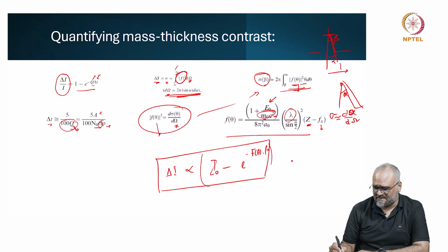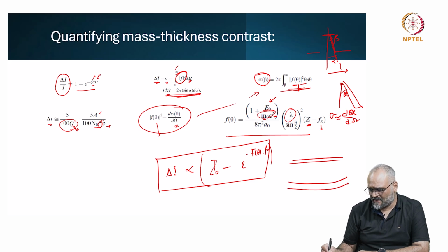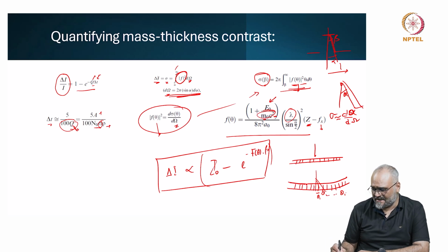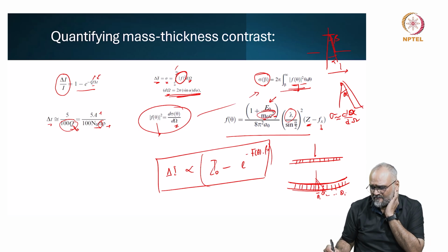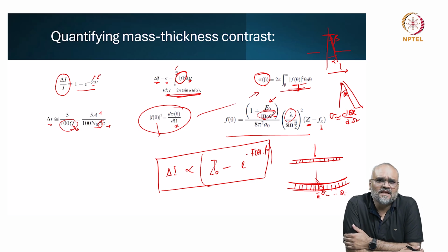Also, if I have a specimen which is very thin, when I place it in vacuum, it tends to somewhat bend a little, and if I look at the arrangement of atomic planes within a specimen which is bent at a certain angle and which is oriented exactly at a specific angle to the electron beam, let us say I have some variation in the angle with these planes here, if I call this as some theta 1 and this is some theta 2 and so on as theta i, this bending also causes a change in the Bragg diffraction condition for the planes that are arranged internally within this specimen, and this results in what is called as bend contours or diffraction contrast, and we see this primarily in a bright field image.